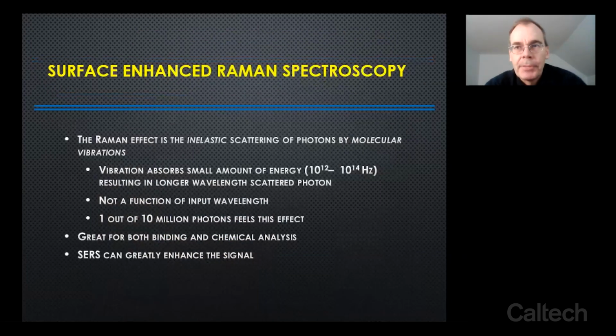surface enhanced Raman spectroscopy. It's one of my favorite techniques because it allows us to see single molecules if we want to. And the idea is that you have a laser beam that gives you light at a very specific wavelength, very accurate single wavelength, and you scatter that laser beam in the material of interest, in tissue samples or whatever you're looking at. And the idea is that the light from the laser, these photons, because of your scattering, they lose energy, and by looking at the energy loss, you can measure the vibrational modes and the bonding structure that identifies your molecules that are surrounding your system.